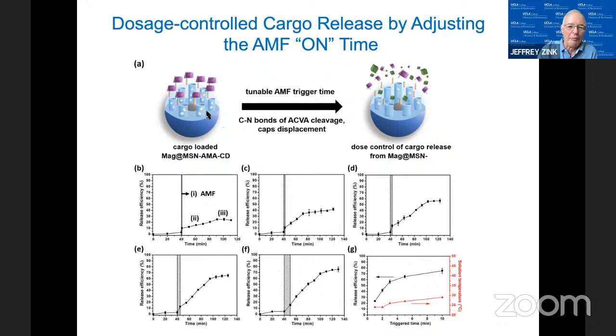With the heating from the magnetic field, then, can cause it to open. And depending how long we turn on the magnetic field, a very short amount of time or longer and longer, shown as B through F down in the bottom here, we can get more and more drug release. And on part G on the very lower right, we can measure the overall temperature in the bulk system as we do this. And so you can see then that the maximum bulk temperature rise is only 4 degrees centigrade as we do this for the longest magnetic field on part. But we can get very good release very quickly.